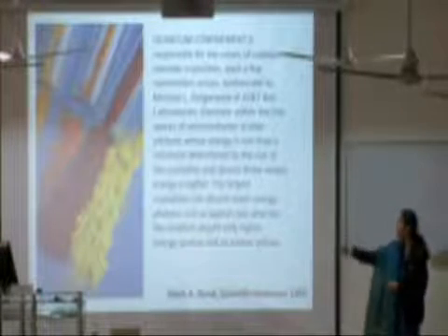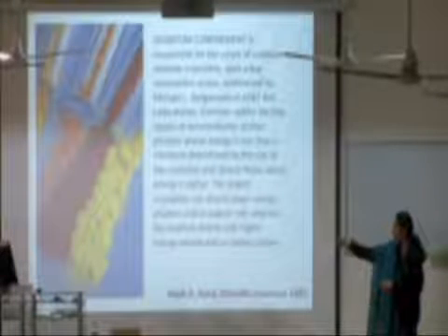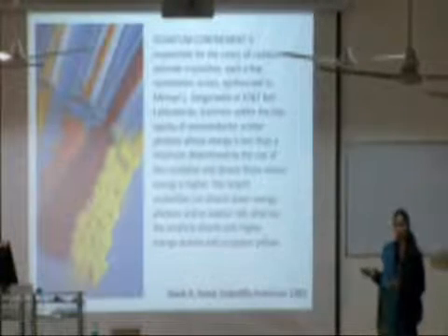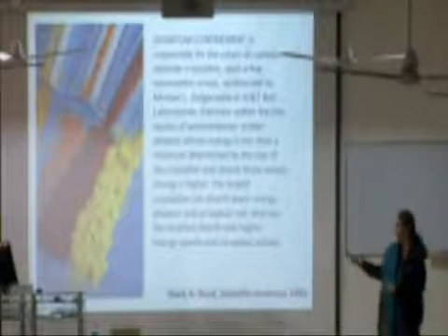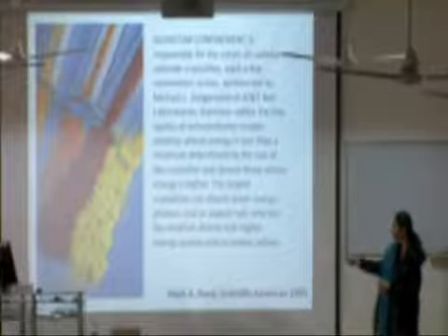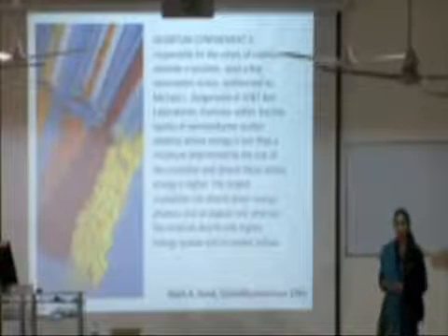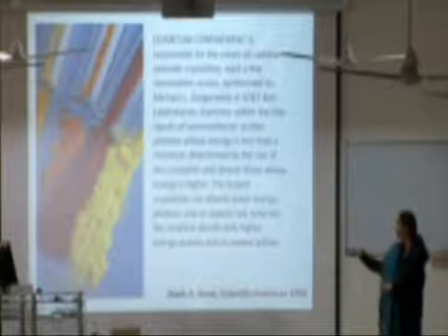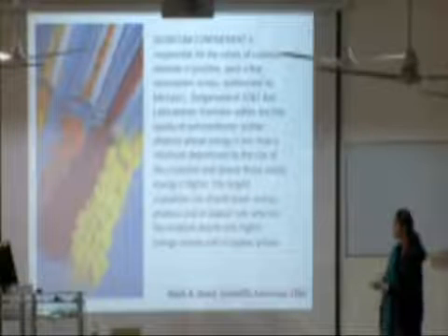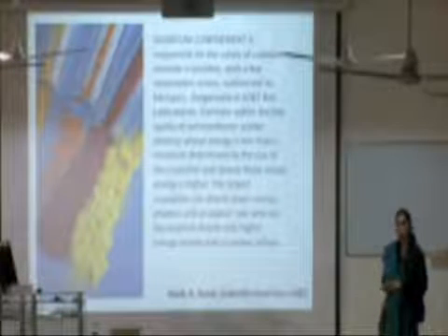And what I'm trying to show in this image is that if you look at the particles on the left side, they're bigger. So the size of the crystallites is larger. And the particles towards the right of the screen, the ones which appear yellow, the crystallites are smaller. So the point here is that the larger crystallites can absorb lower energy photons, and they appear reddish.